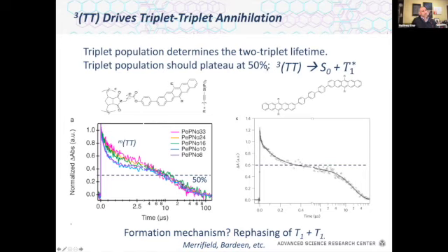But our 3TT state, our net triplet, has a recombination mechanism very similar to Auger recombination in semiconductor quantum dots. And so what should effectively happen if the 3TT state is dominant is that over time, we will lose exactly 50% of our triplet population. And we showed this in a number of systems. This is the one I showed you before. We have quintets. I'm just showing you the normalized triplet population. Over time, we get to a 50% plateau.